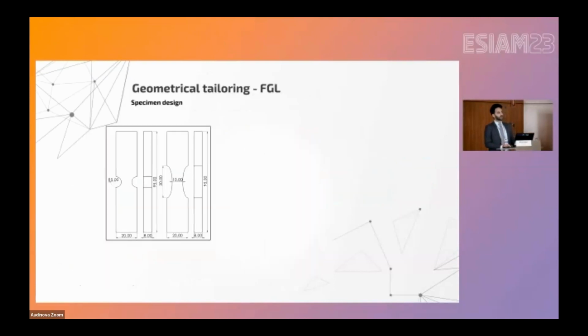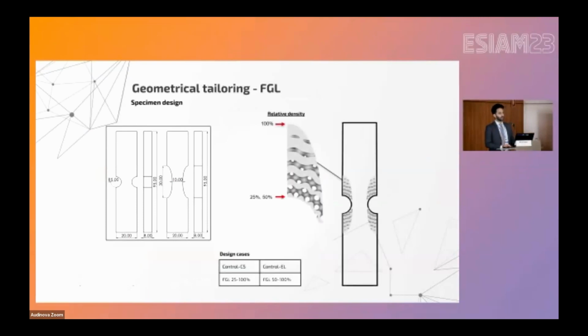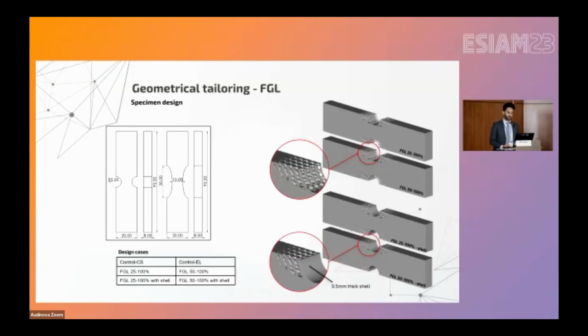We consider two control cases, semicircular and elliptical notches. And in the elliptical case, the larger diameter is 3 times the smaller one. We designed some functionally graded lattice specimens, or it's better to call them tailored specimens because they have solid parts as well, with the same geometry as the elliptical case. In this case, the lattice had a relative density from 25% to 100% and from 50% to 100%. So 4 cases so far, the 2 control cases and the tailored samples.